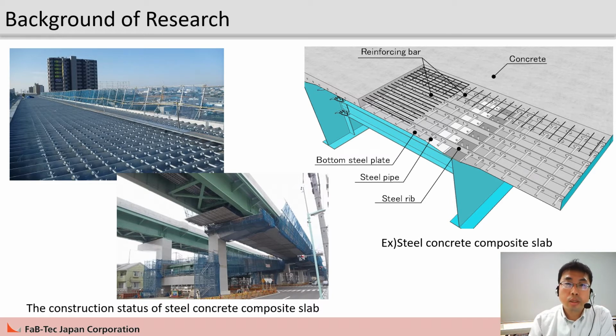Fabtech Japan Corporation developed a rigid type of shear connector with steel pipe that passes through the long hole on the steel rib. The load carrying capacity and durability have been confirmed to be equal to or more than those of headed stud and perfobond rib, because the long hole in the steel rib is filled with concrete. In addition, the photo shows the construction status of steel concrete composite slab. The thickness of the bottom steel plate controls tensile force acting on the slab.